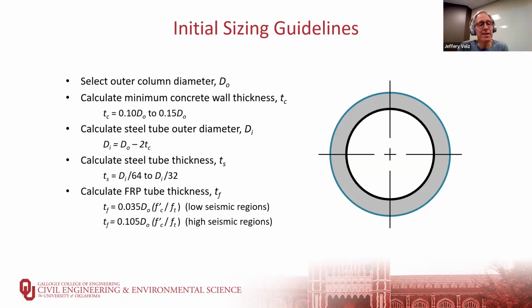And then the FRP thickness is a function of the diameter of the FRP and the ratio of the compressive strength of the concrete, the 28-day uniaxial compressive strength, and the hoop tension capacity, F sub T, of the FRP. And if you're in a low seismic region where you're not going to have as high of strains during one of these hazards, there's a 3.5% for the thickness. And if you're in a high seismic region, such as California or Japan, then you're up to 10.5% of that ratio. And again, these are just guidelines to get you close so that you can then do a more detailed analysis.